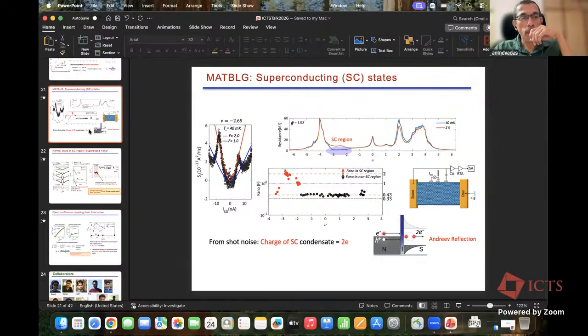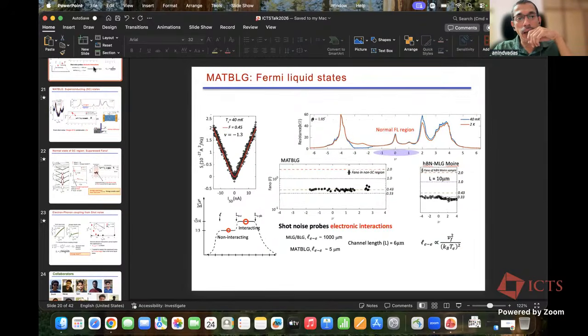Right. So yeah, we just had an estimate about this. I think this slide tells you about the estimation. I think the important parameter is that the Fermi velocity in magic-angle graphene based systems is almost 2 orders of magnitude smaller. Because of its flat band nature, that brings the electron length scale down much smaller compared to the conventional graphene system. Yeah. Thank you.